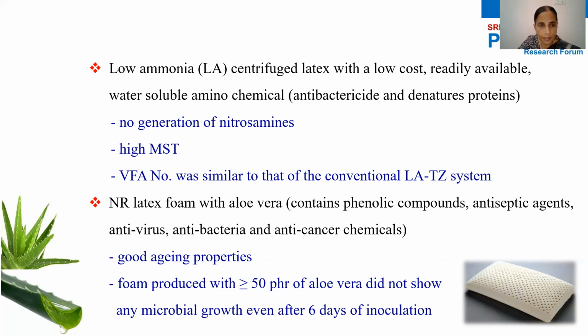In another study, natural rubber latex foam was produced with aloe vera. Aloe vera contains phenolic compounds which are known to act as antioxidants. And also aloe vera contains antiseptic agents, antivirus, antibacterial, and anti-cancer chemicals. The latex foam produced with aloe vera exhibited good aging properties. And also the foam produced with greater than or equal to 50 phr aloe vera did not show any microbial growth even after 6 days of inoculation.